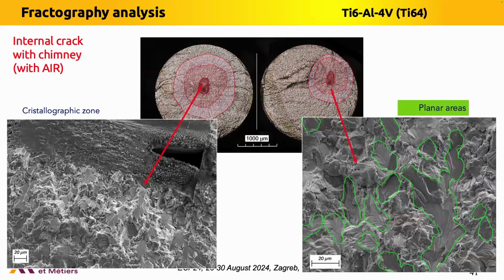Now, if we look at the specimen with air inside the crack, you can see here the pre-crack and the chimney. Around this pre-crack, there is a dark area, classically in literature, with a very crystallographic zone. And in the bright facets around, we observe very planar areas, very frequent and very large compared to the initial facets we have seen in the other configuration.